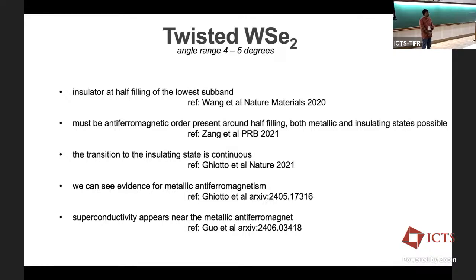And I also wanted to know, in this superconducting phase, if you apply a strong magnetic field and suppress the superconducting state, do you see any antiferromagnetic fluctuations persisting in the normal state in that region? Yeah, so that was one of the slides I flashed: if you go to 100 millitesla where superconductivity is suppressed, and you look at the phenomenology, you see evidence in the Hall effect for this Fermi surface reconstruction. And so, yes, indeed, we do think so. I see. Thank you.